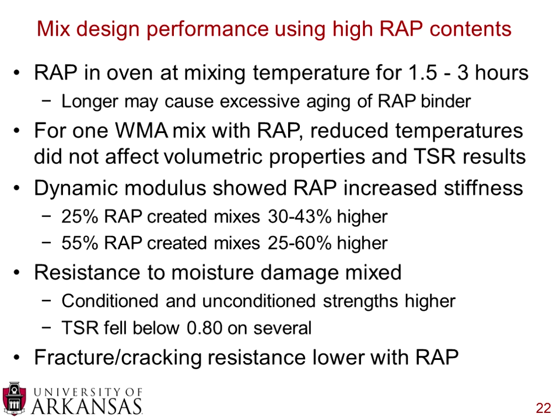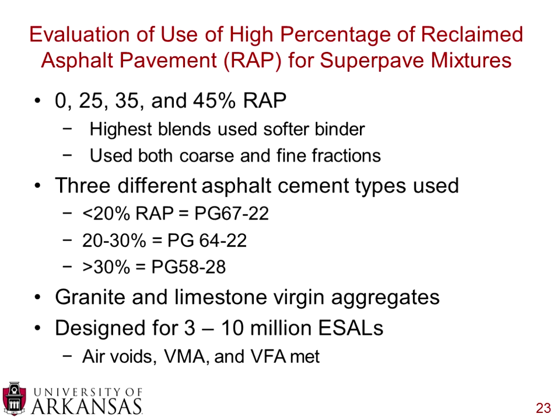And they also did some cracking resistance using fracture testing, and they found that adding RAP decreased the fracture or the cracking resistance of the mixtures. So overall, the mixtures were a little stiffer. They had higher tensile strengths, but the ratio of the conditioned to the unconditioned was lower, and the cracking resistance using the high RAP was also lower.